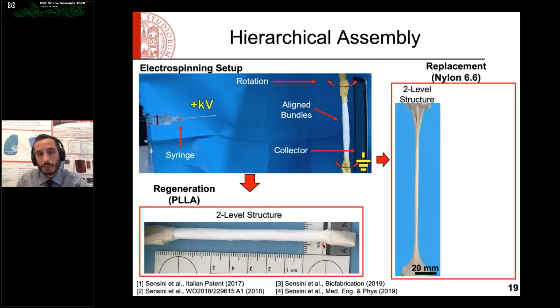But using instead the ring-shaped bundle shown before, it was possible, in the case of nylon 6/6, to obtain a two-level hierarchical structure like that, in which we can also obtain looped ends suitable to better fix these structures, for example, in the testing machine, in a bioreactor, or in the body of the patient, to help surgeons suture the extremities better.